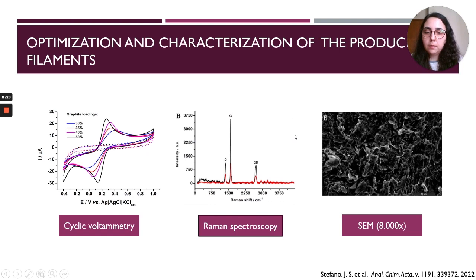We also characterized the filaments using Raman spectroscopy, and you can see the peaks related to graphite are present on the surface, both for the filament produced, which is shown in black, and also for the printed electrode, which is shown here in red. So D, G, and 2D are all present in both samples, showing that there is some graphite in the surface, which is what we desire to acquire.